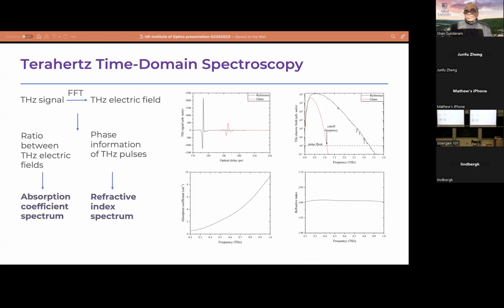Typically, you start with the terahertz signal, and with a Fourier transformation you get the terahertz electric field, and from there you can extract the absorption coefficient spectrum and the refractive index spectrum. You can see this is just raw data of a simple piece of glass we put inside. We use a reference of high-purity nitrogen gas. You can see how you can collect the data spectrum and the data set, and also plot absorption coefficient and refractive index over the frequency range.